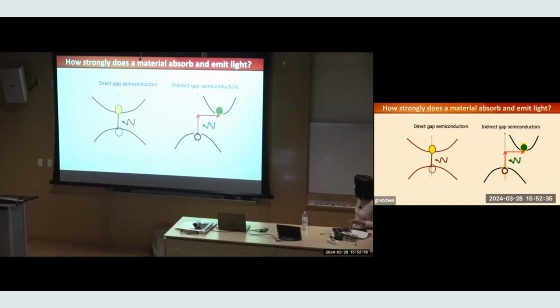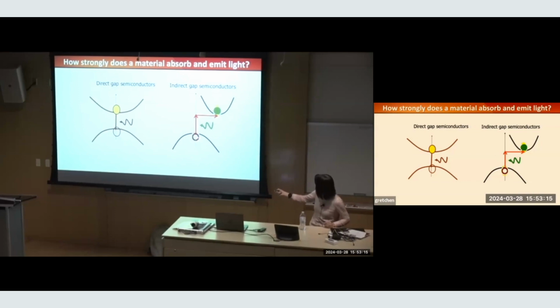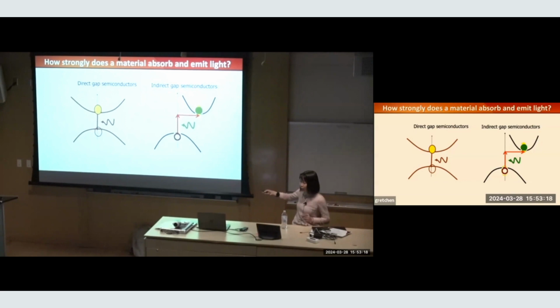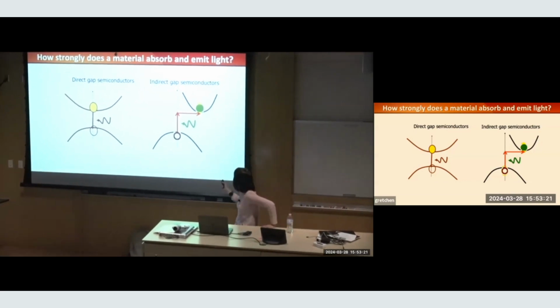So in semiconductors, there are 2 important classes: direct gap semiconductor and indirect gap semiconductor. It just means whether the top of the valence band is aligned with the bottom of the conduction band in the quasi-momentum space. In a direct semiconductor, light carries very little momentum compared to the whole range of the Brillouin zone in the solid. And so anytime you involve light-matter interaction, it's typically a vertical transition. And if you have an indirect semiconductor, for example, silicon, you're not going to be able to make a transition from the top of the valence band to the bottom of the conduction band directly. So there's some other process that needs to be involved to satisfy momentum conservation.